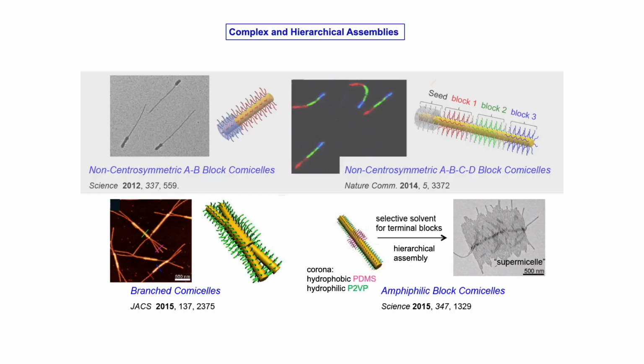If you put this in a solvent that is a poor solvent for the hydrophobic center but a good solvent for the hydrophilic ends, then you can get these to self-assemble into supermicelles—so it's a micelle made from micelles. And now you're getting up to really long length scales, multiple micrometers in length.